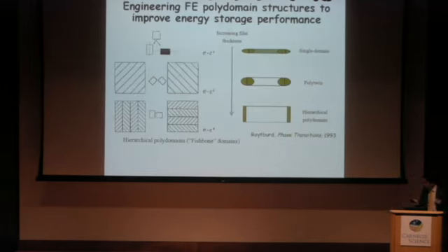So, a little bit of background about the elastic domains. Dr. Roytburd gave a very nice background, so I'm not going to spend too much time. But here, we know that as you grow a strained film on a substrate, the elastic energy increases with film thickness. For a very thin film, of course, you don't have interfaces; it's strained uniformly across. But when you grow the film above some critical value, you form polydomains as a way to relax the epitaxial stress energy. As you grow the film even thicker, you form higher-order, so-called hierarchical polydomains. It's kind of like fishbone domains.